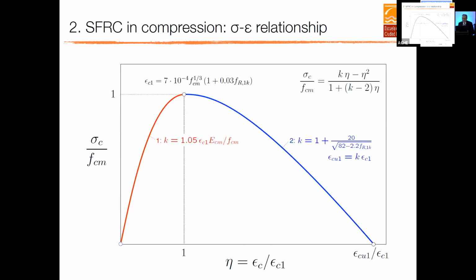Actually, it is a very simple thing because we use the same formula, the same equation of Sargin, which is that one in this corner. It is exactly the same one as for plain concrete, but we slightly modified the critical strain for the peak. Here you see there is a parenthesis which is multiplying. It depends on the residual flexural strength for an opening of 0.5 millimeters, the characteristic value.